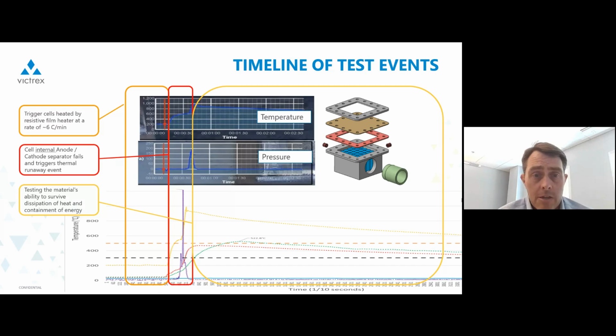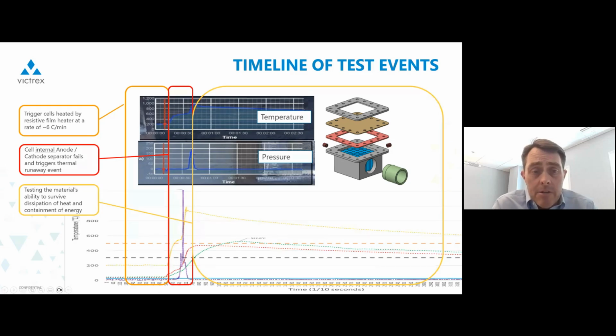It builds upon itself, and then it reaches a maximum point of maximum temperature and pressure, generating a cascade of events throughout the rest of the battery array inside the box, and that's your maximum release of energy. The rest of the time is being spent really testing the ability of the material to survive dissipation and containment of that energy. So, the first 2 sections here are build up to the trigger point, trigger the catastrophic battery failure, and then the rest of it is contain and dissipate the energy.